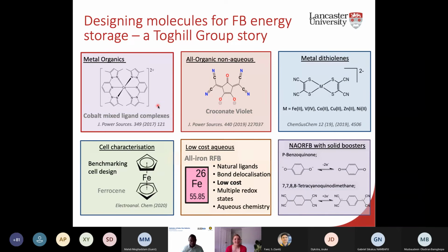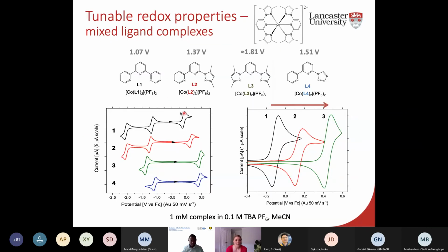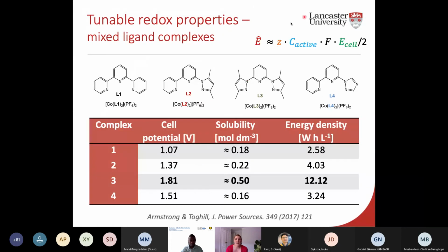Essentially, what we found is that while your voltammetry might look fantastic, and you can see we get lovely reversible voltammetry for these species, so you think, I can have a battery where I have this system against this system, and I can improve the voltage window and the separation of these two things, increase my energy density that way. I can also improve the solubility. I can get a massive increase in what my energy density is going to be on my solution of my species by just making these tweaks to the actual engineering of those molecules.